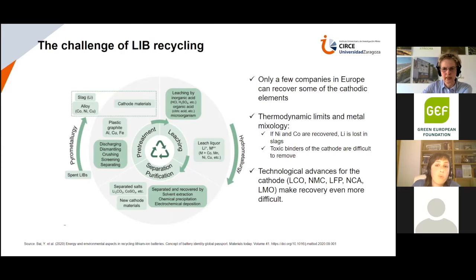Then the electrode is recovered, all right? And the rest is crushed and screened to separate the plastics, the graphite, and the metallic components. So once we have this crushed material, which is an entropic mixture of many elements, then it follows a pyrometallurgical process, usually, and this involves high temperature smelting to recover nickel, cobalt, or copper. However, all the lithium is lost in the slags. So if you want to go further, then you should